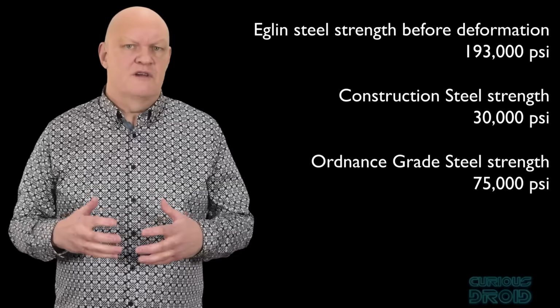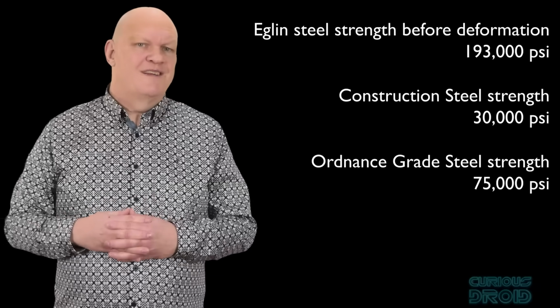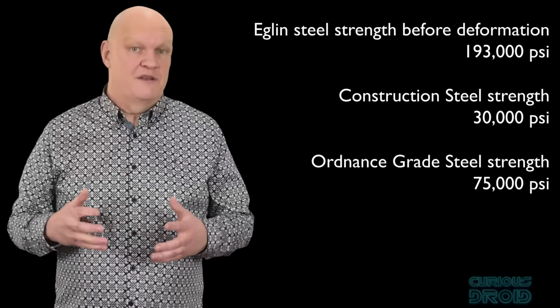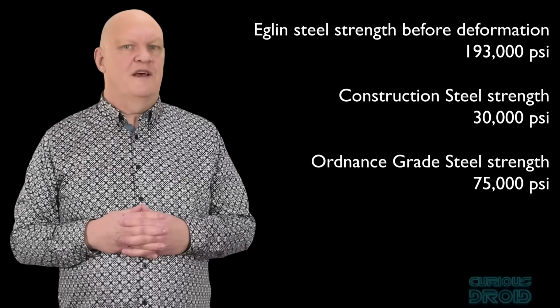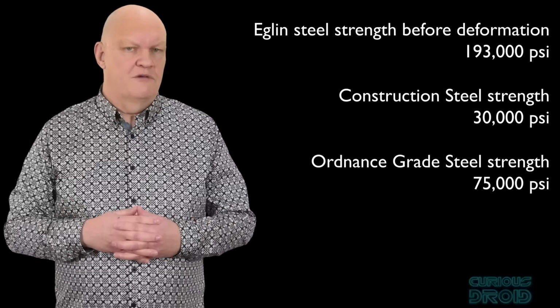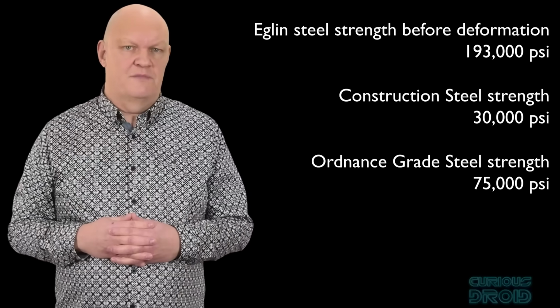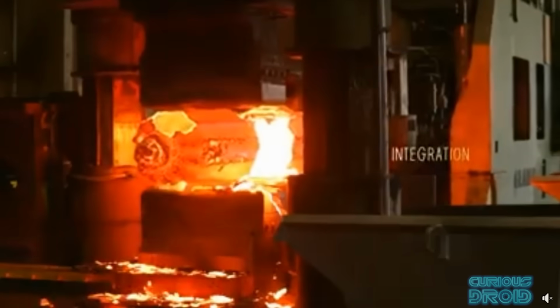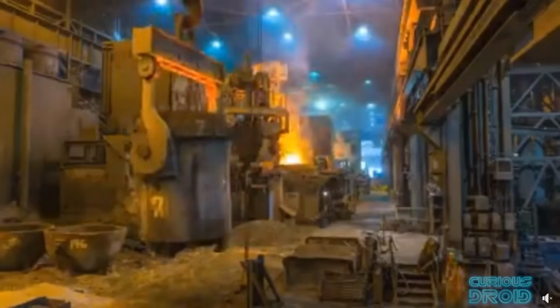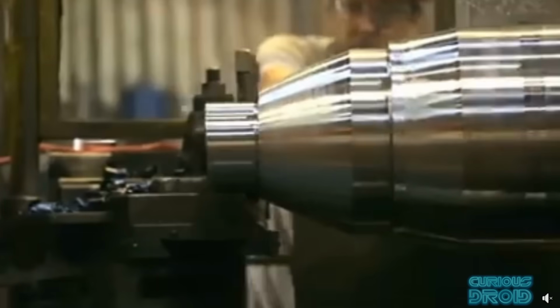It has a tensile strength before deformation of 193,000 psi compared to construction-grade steel of 30,000 psi and ordnance steel for gun barrels of 75,000 psi. Although Eglin is the gold standard, it has now been superseded by USAF 96 steel, which has similar properties but is easier to produce and work with.